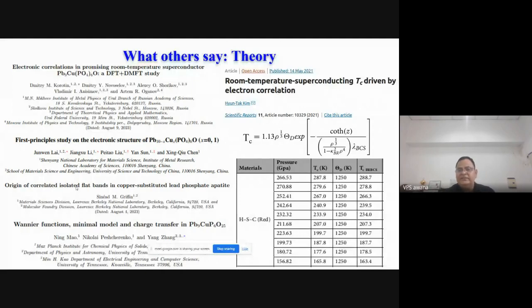Then there is another study from 2021 by this LK inventor H.T. Kim, where he calculated BCS clubbed with density functional theory, and he calculated that in hydrogen sulfides or carbon dioxide samples, the lighter elements, the TC can go up to this range because theta D is of course about 1000 Kelvin, and at the same time different correlations take place in the system, and with higher theta D and the right kind of density of states and within the pressure limits, it can show a TC of 100 or 200 or 300 Kelvin.